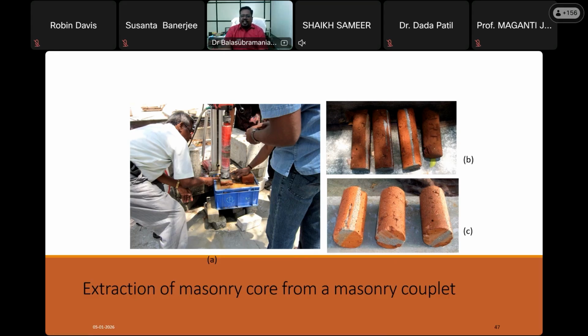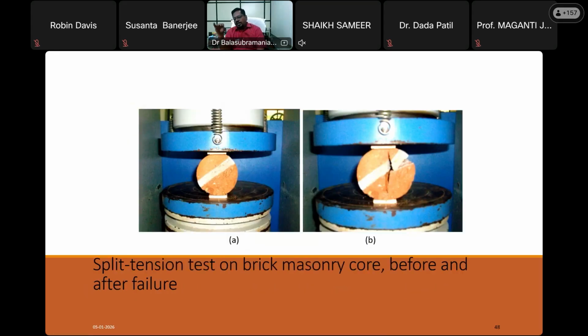To that level we can trim, and then carry out this split tension test using the compression testing machine with the inclined bed joint, because we are talking about diagonal tension, right? Diagonal tension failure actually depends upon the direction. As I told you, it will initiate in the middle and extend to the periphery. The diagonal tension crack line will be inclined to the bed joint. So depending upon the pier's length to height ratio, we can determine the angle of the bed joint. Typically, or generically, we can use a 45-degree angle bed joint and carry out the test.